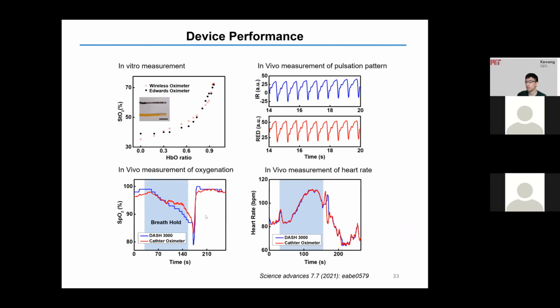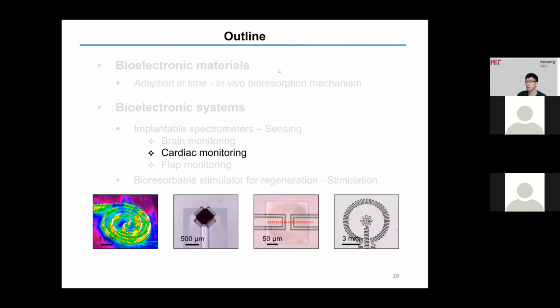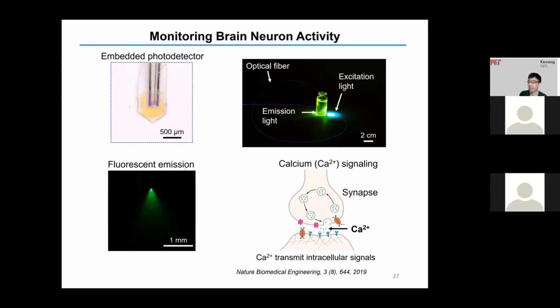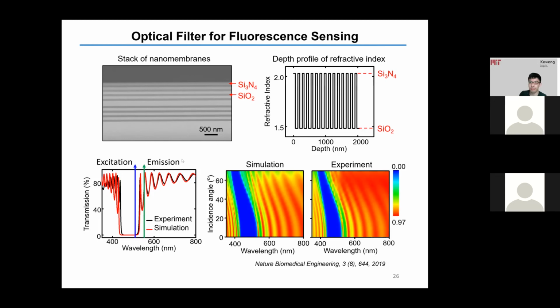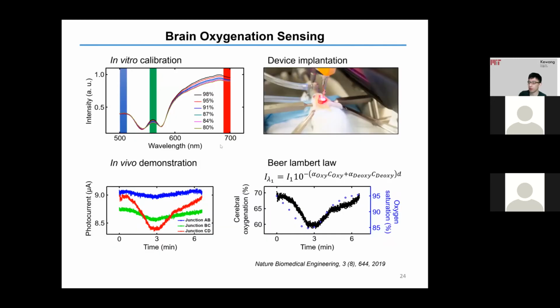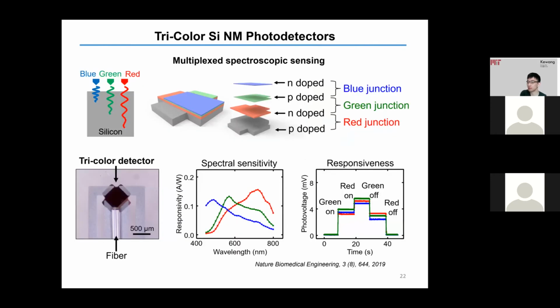Yeah, cool. And so silicon as a transient material was discovered about 8 to 10 years ago from the postdoc groups I was fortunate to be studying. The finding is based on the hydrolysis reaction of silicon, because the reaction rate is extremely slow. Previously we were all using silicon as a bulk material, silicon wafers, usually with a thickness around 500 micrometers. Compared to such a scale, the dissolving behavior in water is almost negligible.